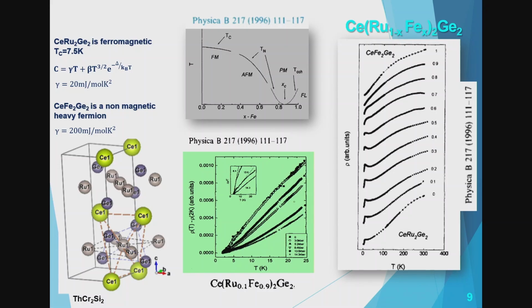So I want to talk about the work we did in the beginning, which was with iron doping the cerium, ruthenium 2, and germanium 2. And I did the complete doping, measuring resistivity, and you see that the material goes from a ferromagnetic to a non-magnetic system, passing through a quantum critical point, as I told you. And this system is magnetic, not heavy fermion, but it becomes a heavy fermion as you dope with iron.